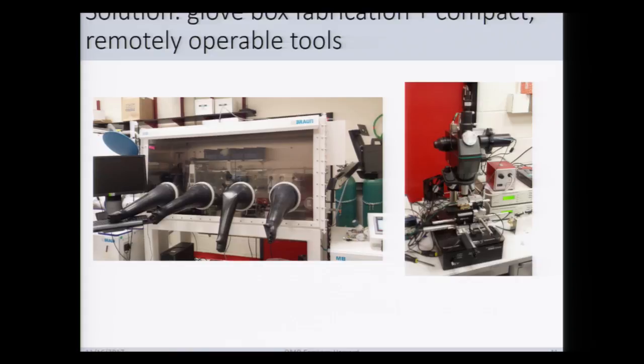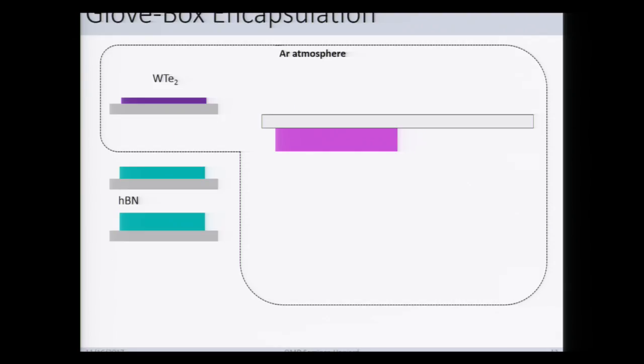And what we set out to do, and we're not necessarily the first ones to have done this, but we built our own glove box system where we have an argon environment that's protected from the atmosphere outside, where levels of oxygen and water are highly suppressed. And inside we can have a microscope and remotely operated transfer setup so that we don't have to have our hands in the gloves all the time, and allow us to do some protection schemes to do fabrication on these systems. So the scheme is something like this.